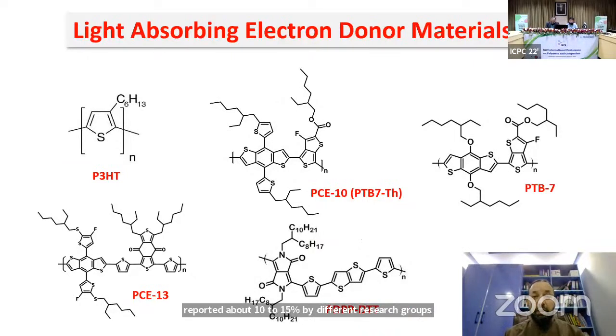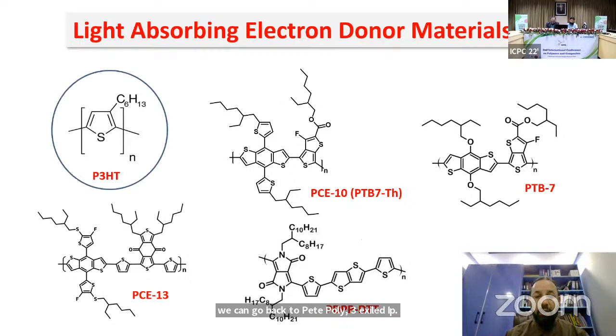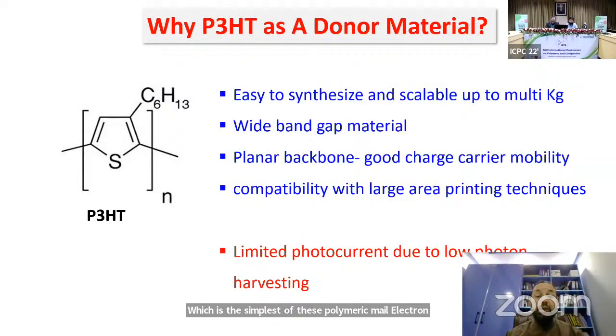So once we had these electron accepting materials, we decided, okay, let's see if we can go back to poly-3-hexylthiophene, which is the simplest of these polymeric electron donor materials. Why P3HT? Because it's very easy to synthesize and possible to scale up to multi-kilogram scales. It's a wide band gap material and has shown good charge carrier mobilities. And more interesting is that this material has already been tested for large area printing techniques, showing good compatibility.